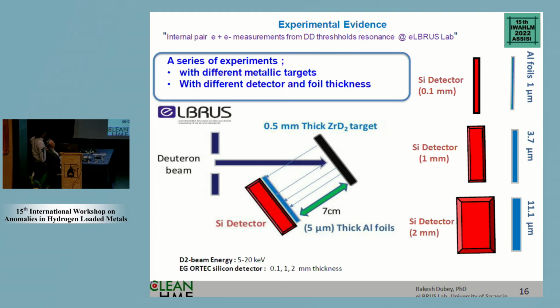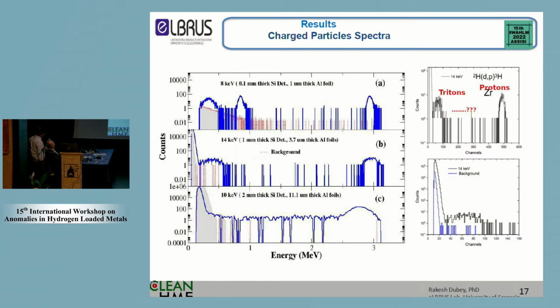However, for further confirmation, we performed a series of experiments with different metallic targets and different detectors with different foil thicknesses. The foil thicknesses were like this. First we started with 1 micrometer, and then 3.7 and 11, and correspondingly we took thicker and thicker detectors, and the energy range was almost the same. So what you observe is that for the thinner detector with the thinner foil, you can see all three charged particle spectra, and if you compare with the backgrounds, almost the background is there in this region. But if you look at the thicker detectors and slightly thicker foils, in this region, with respect to background, there are some genuine counts.